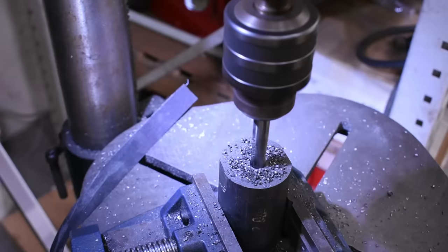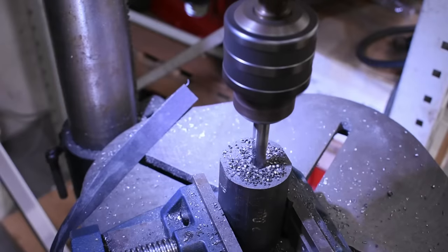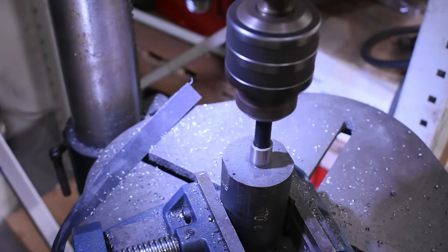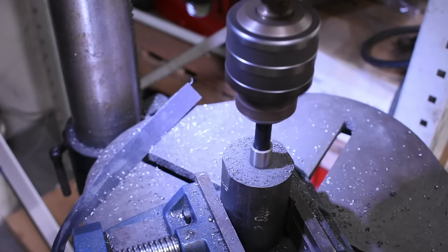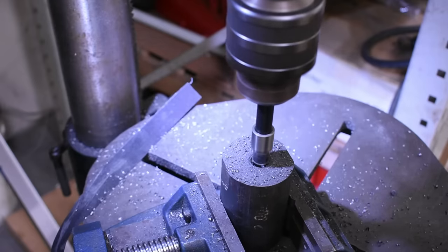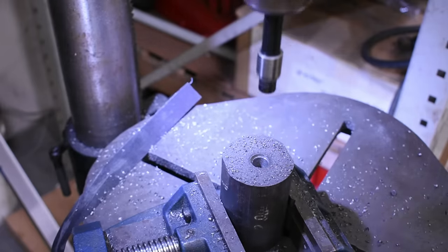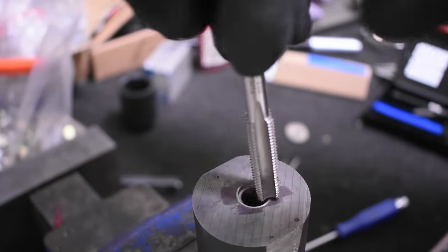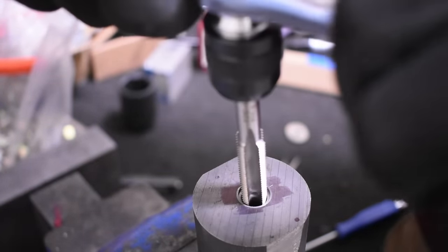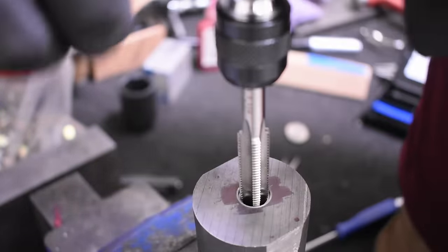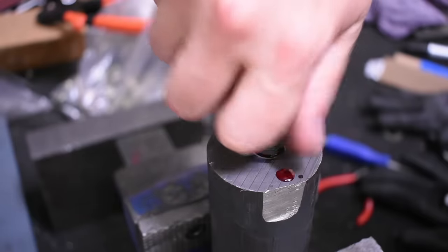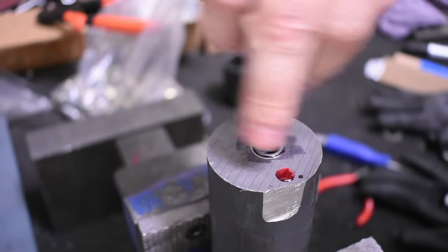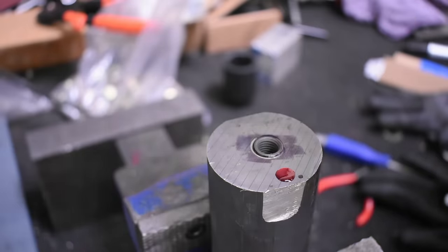You use these with the included drill per usual. Then you use this counterbore cutter that has a stopper so you can feel when it's deep enough. Works pretty simply. I don't think it would be that much more difficult with the hand drill. The counterbore allows you to install the insert with its top lip flush or just under flush with the material. Then you tap the hole and you thread in the insert, which is pretty loose at this point and can be done by hand or with the install tool as they probably intend.